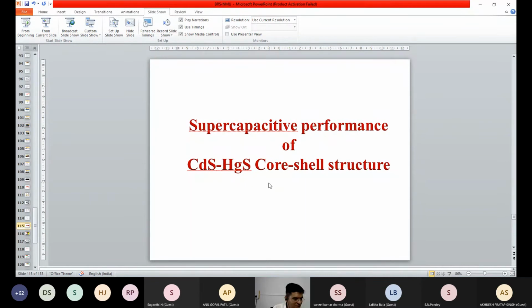Then again, we used this CdS nanowire as a core to form HgS as a shell. We formed CdS as a core with HgS as a shell, so that it forms the core-shell. One material is inside and above it there is another material. CdS is in the nanowire form, and on it we have made another material to form the core-shell. So this is a nano heterostructure type.